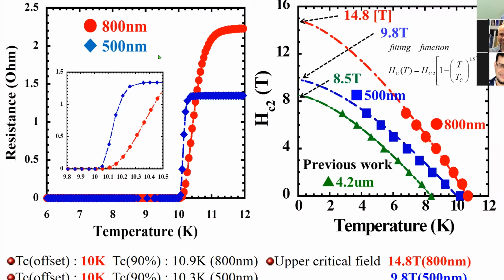We also applied magnetic field to see what happens to HC2. According to the thickness, the thin films show very high magnetic field resistance, about 15 Tesla. So I think this material is very strong, very resistive to high magnetic field.